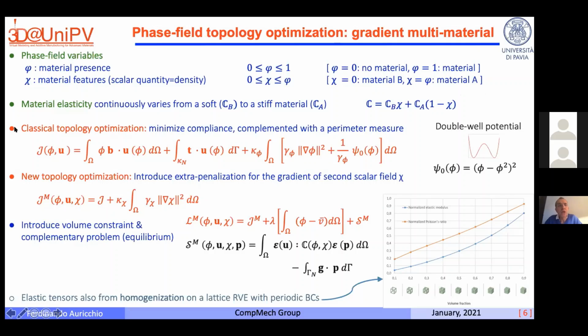Okay, so using a phase field approach, we introduce a functional where you have your standard compliance, which are basically the two integrals reported here, and then we have also a very classical measure of the perimeter, which is associated with your first variable. However, since we have a second variable, we also want to penalize the gradient of the second scalar field. So basically, we don't want to have the possibility of a structure where you jump from material A to material B too many times. So we penalize this other gradient of the second scalar variable through a parameter that we call kappa chi, okay?